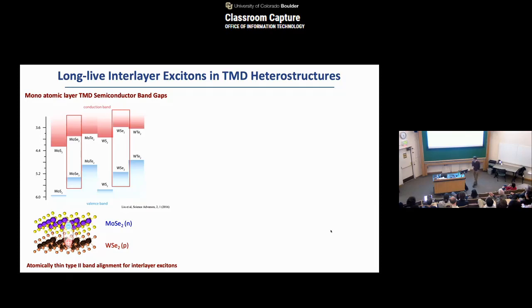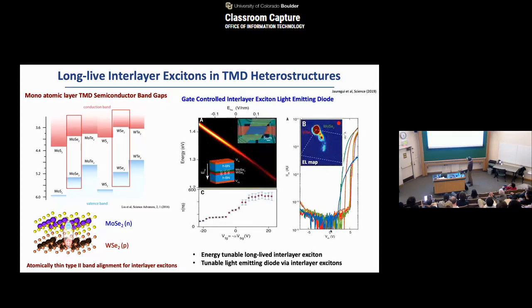So what we can do is make the device. I already showed one example of this device, I think: the atomically thin PN diode I mentioned, right? Optically, that's basically a type 2 alignment. So when you shine the light, indeed, you get this interlayer exciton forming, and you can explore it by photoluminescence. Shine the light over the band gap and see how this exciton is emitted back, and look at that energy scale. I know what the interlayer exciton energy scale is.